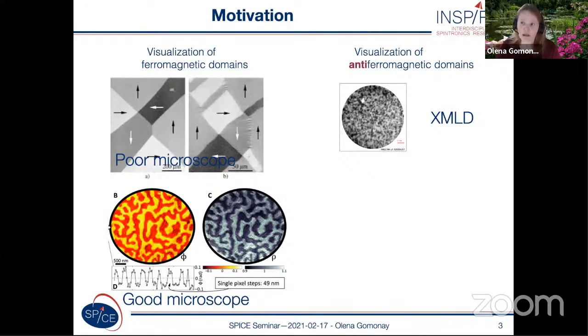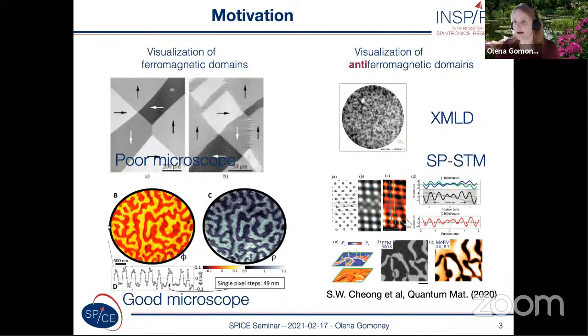But if you try to do the same thing for antiferromagnetic domains, then you end up with pictures taken at a synchrotron by the XMLD technique, which is extremely involved, or by other involved techniques like spin-polarized STM, which needs monolayers and very specially prepared surfaces and samples, etc. So antiferromagnets are very interesting for spintronics because they are robust to external fields, but this makes them very difficult for direct observation.